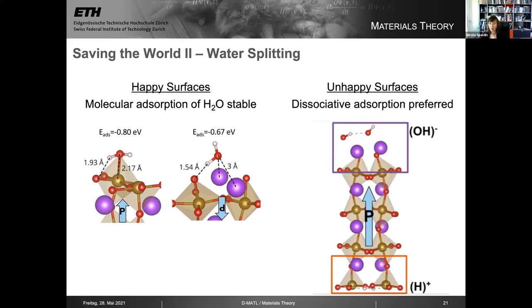On the unhappy surfaces, we still have adsorption. There's still a negative adsorption energy, but this time it's for the dissociated ions of water. And of course, the OH minus ions adsorb on the positive charge surface, which is the bismuth. I had that on the bottom before, I apologize for that. And the H plus ions adsorb on the negatively charged FeO2 surface.